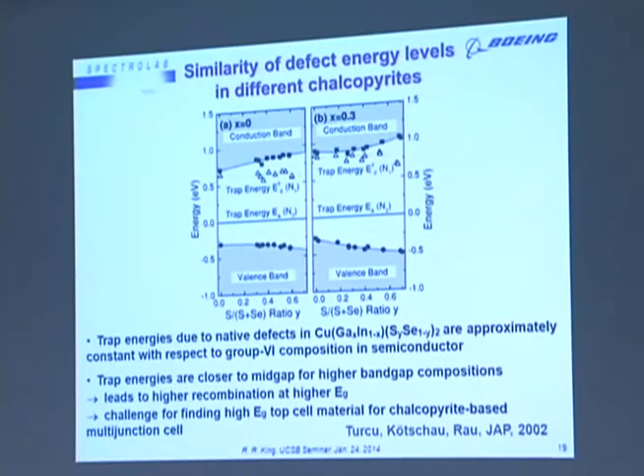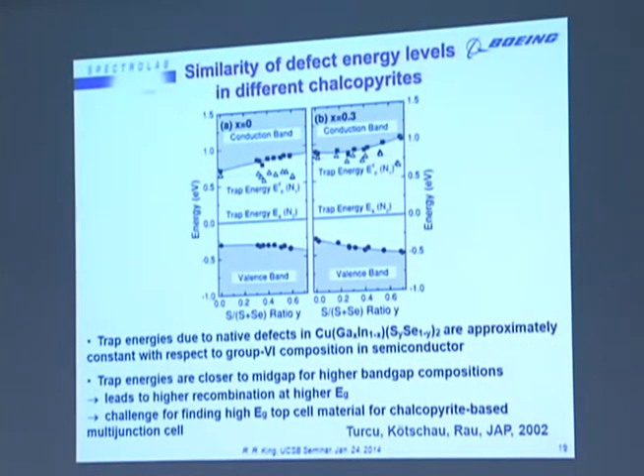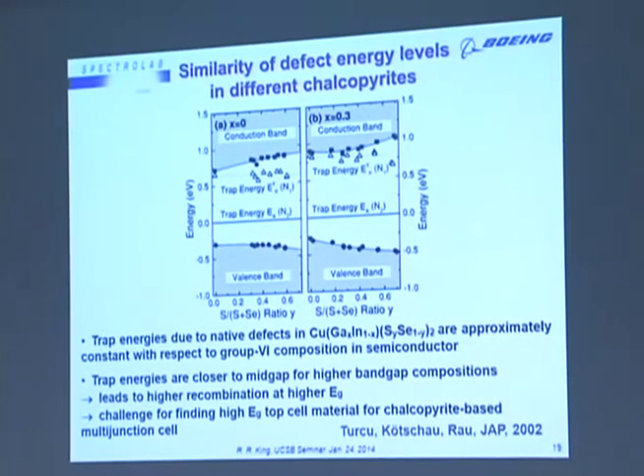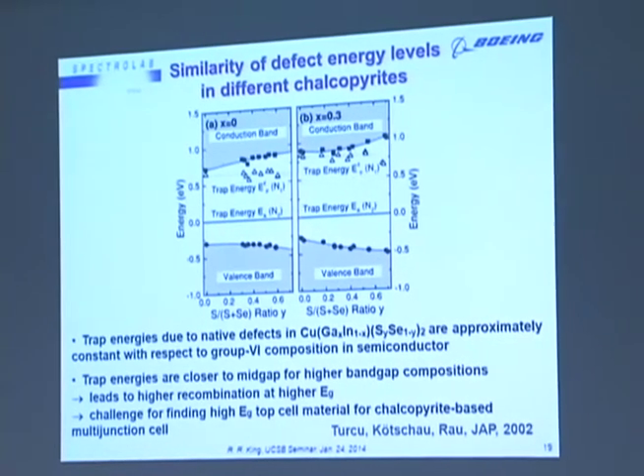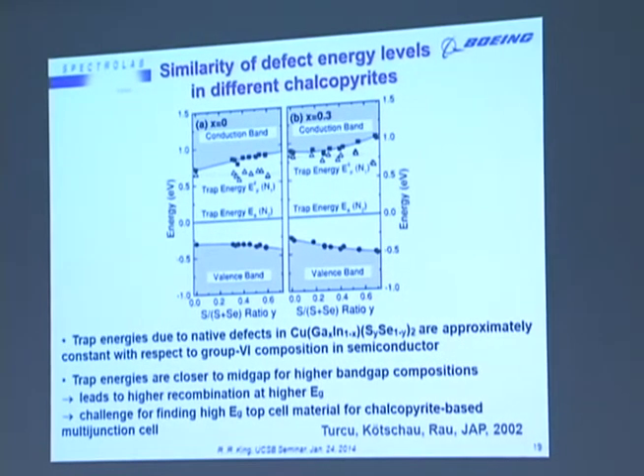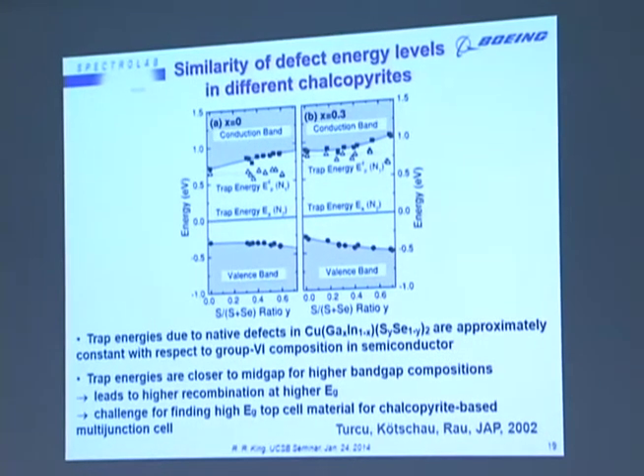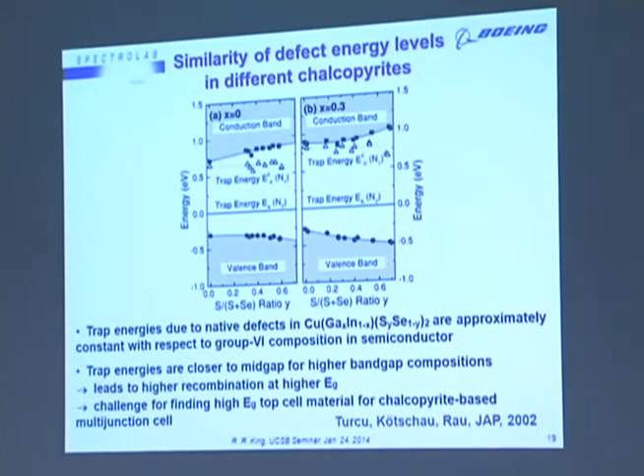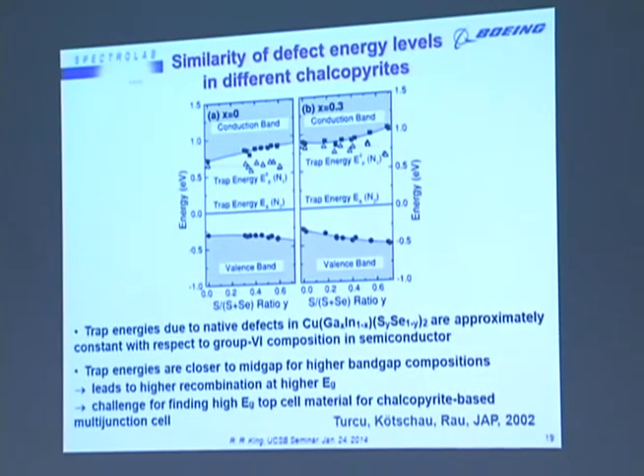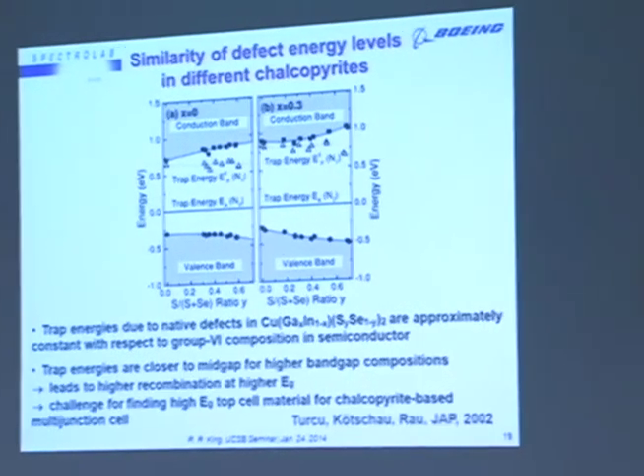increasing the sulfur composition increases the band gap. So now these trap energies, instead of being very near the band edge, are now closer to the mid gap, and therefore have higher recombination than they did in the copper indium diselenide. This is one of the challenges, but not the only challenge associated with finding a high band gap chalcopyrite material that could be used potentially in tandem to make a multijunction cell in combination with the 1 eV copper indium diselenide.